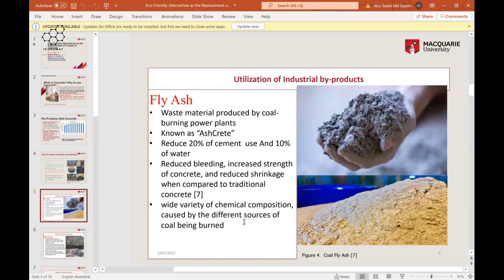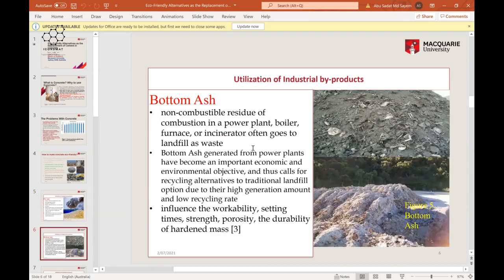But sometimes the problem with fly ash is that its wide variety of chemical composition affects how its products come out. So it's very vulnerable. Besides that, we have bottom ash, which is also a power plant product and really goes to landfill. But after using bottom ash in concrete, it helps to increase the workability, setting time, and strength. And it can be a good substitute for cement.